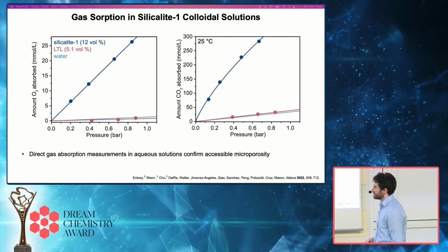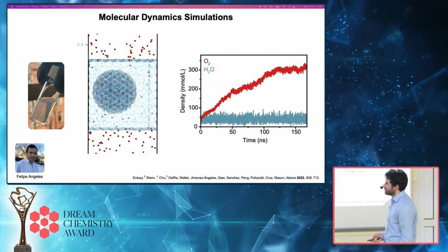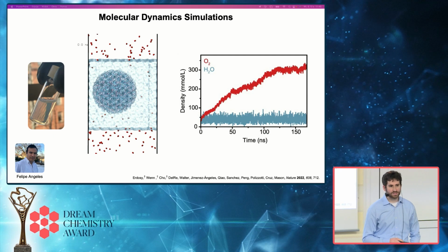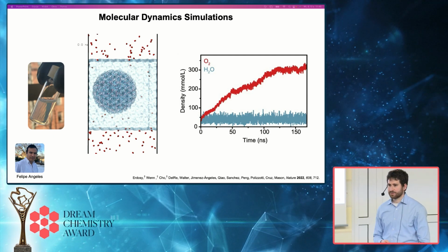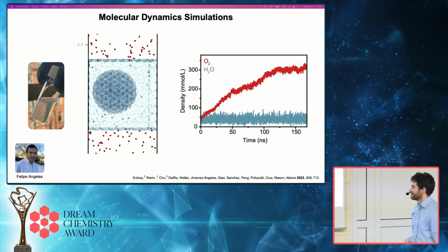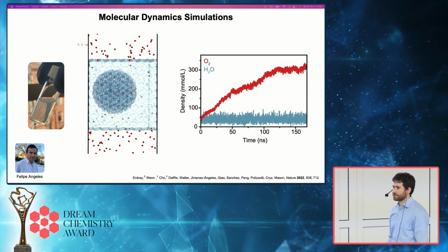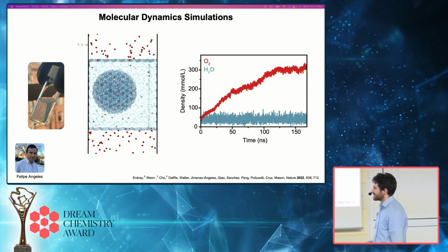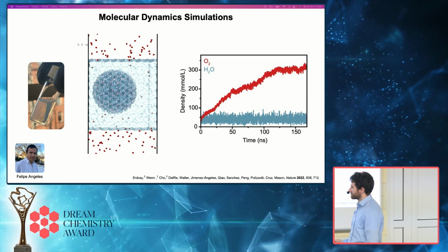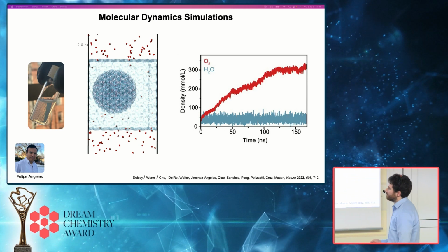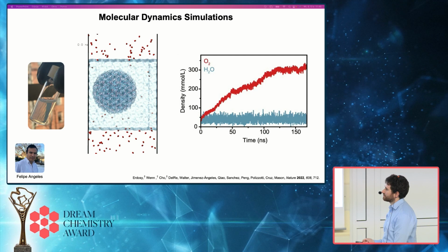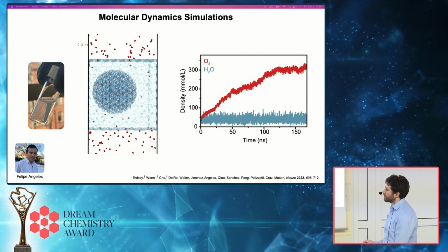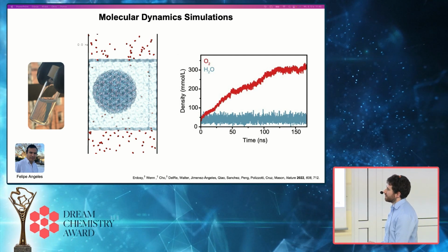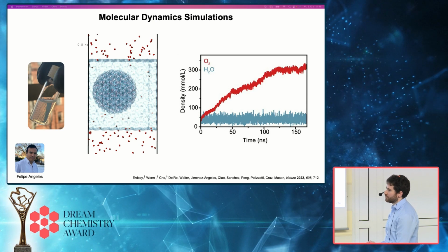And so this got us really excited. We also worked closely with some collaborators at Northwestern University, particularly a group of Monica Olvera de la Cruz, to do some molecular dynamics simulations to actually visualize exactly what's going on when we're doing these kinds of experiments. And a really talented research scientist, Felipe, and her group built a model of a 10 nanometer Silicalite 1 nanoparticle, which you can see right here, which is surrounded by liquid water and in contact with a bulk gas interface.